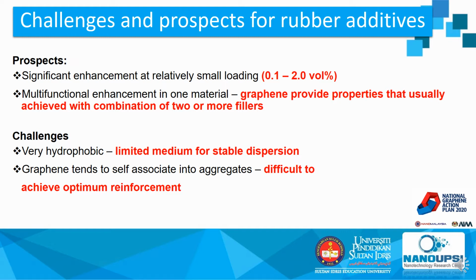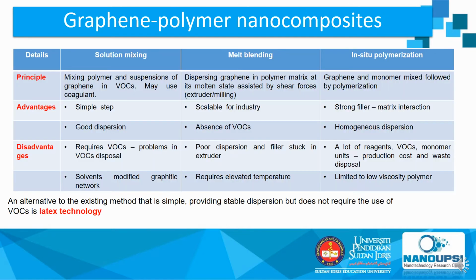However, the major challenge towards this application is that graphene itself is very hydrophobic. It's because of limited dispersibility in the polymer matrix. Another reason is that graphene also tends to self-associate, and as a result it produces aggregates and it is difficult to achieve optimal reinforcement.